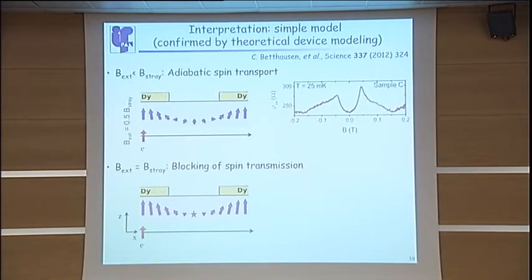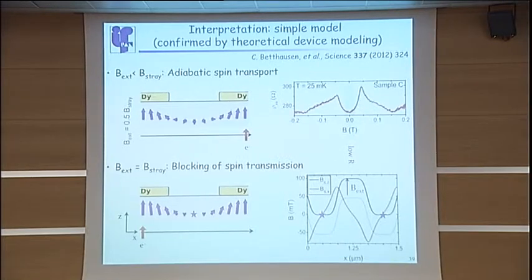period, the distance. Now, once again, how it works: the electron coming from left to right without the magnetic field adjusts its spin direction and can freely move to the right. So you are getting low resistance. If you produce these degeneracy points, an electron going from source to drain comes to the moment when it would have to change its direction suddenly, and therefore this leads to the Landau-Zener transition between spin up and spin down levels, and also leads to the reflection, so to the high resistivity region.